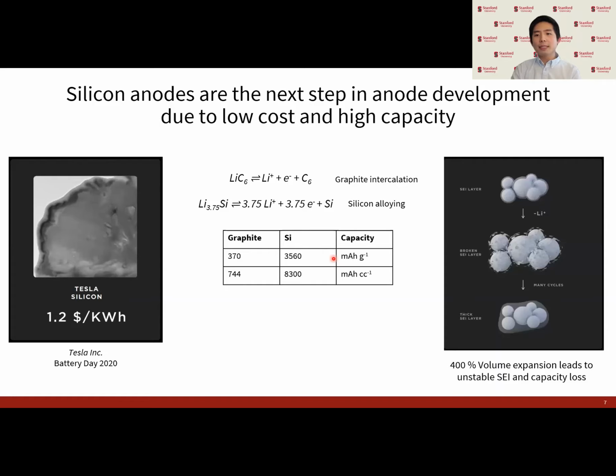But the problem with the silicon anode is that high lithium storage capacity results in high volume expansion. And that exposes new surfaces for SEI formation during each charge and discharge. And after many cycles, this SEI grows very thick and resistive and starts to consume a lot of lithium ions. So now the question we have is, using cryo-EM, what kind of new insight can we start to gain into the silicon SEI?